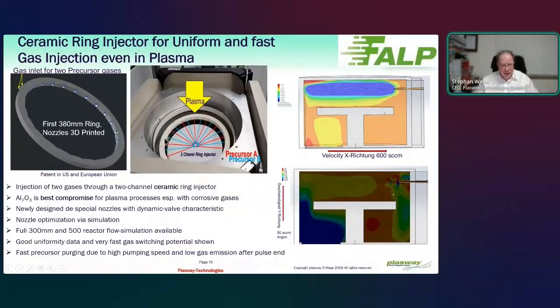We have this ceramic gas ring, and here you see just the nozzles, and these nozzles are made by Lithoz 3D printing technologies. Together with some special flow dynamic simulation of the complete chamber, we were able to control in a good way how the gases go into the chamber. The specialty of this ring is that we can bring the precursor A on each of these red nozzles, and the precursor B on the other nozzles. So the gases will never interact with each other. Nozzle A goes in with this nozzle, and then precursor B with the second nozzle.